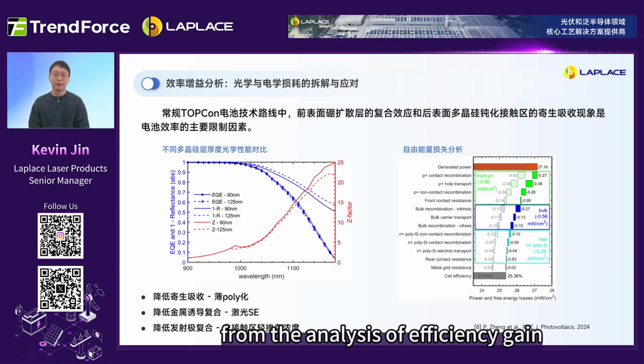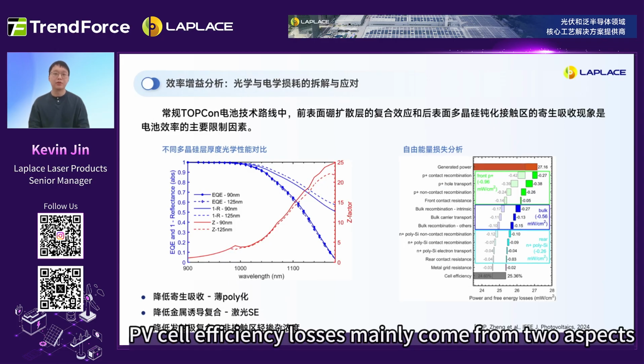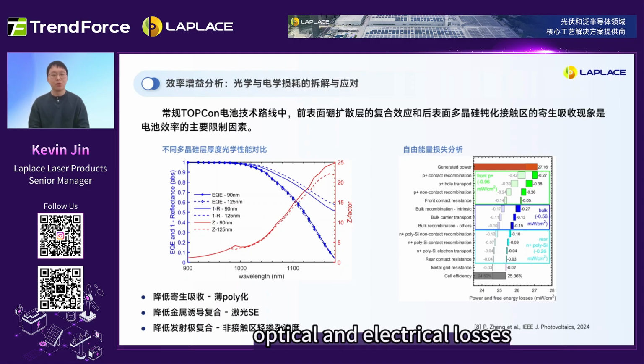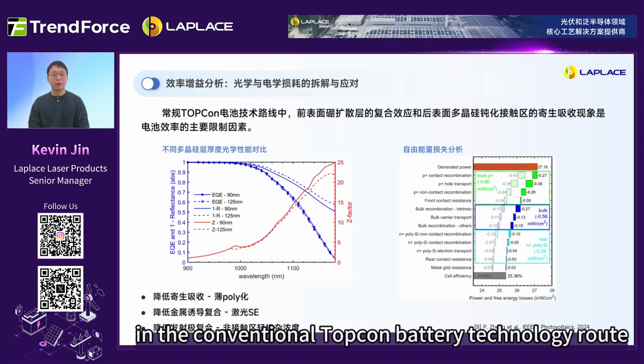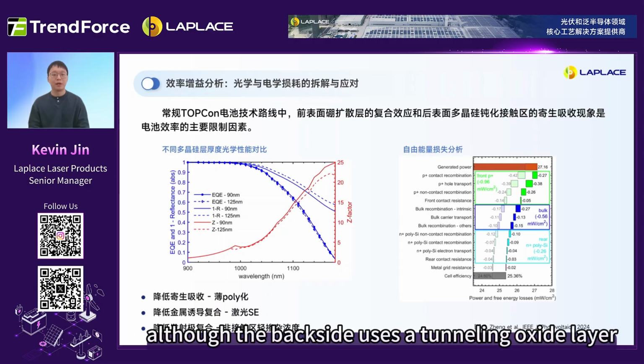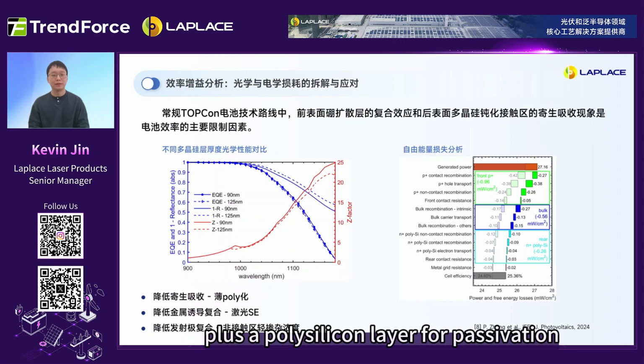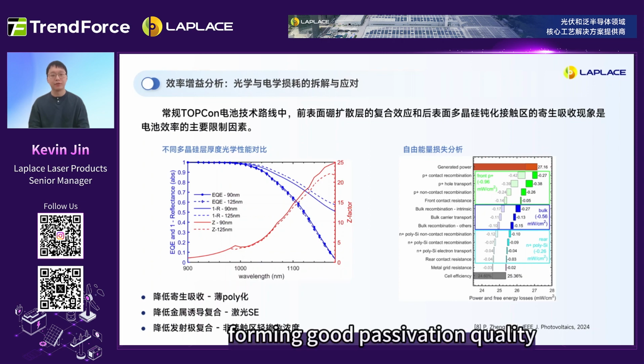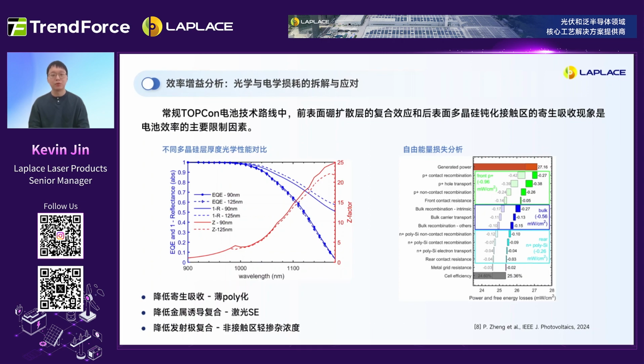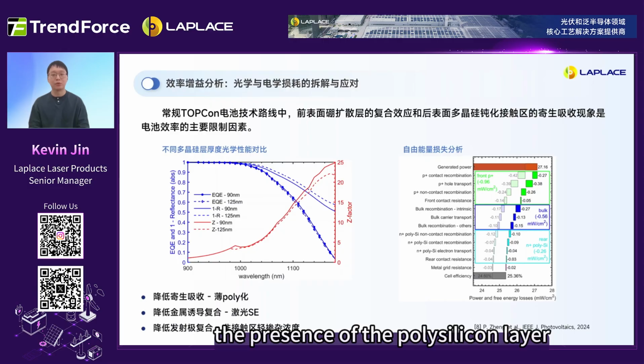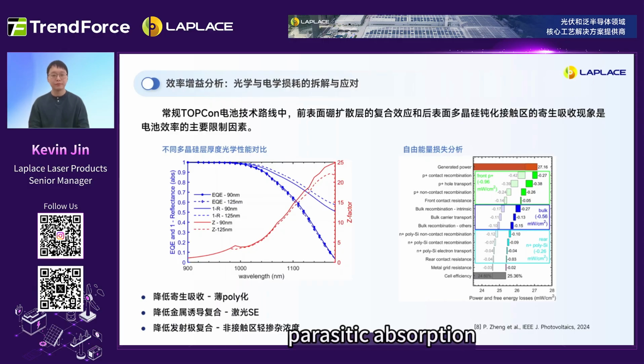From the analysis of efficiency gain, PV cell efficiency losses mainly come from two aspects: optical and electrical losses. In the conventional TOPCon battery technology route, although the backside uses a tunneling oxide layer plus a polysilicon layer for passivation, forming good passivation quality, the presence of the polysilicon layer causes significant parasitic absorption.